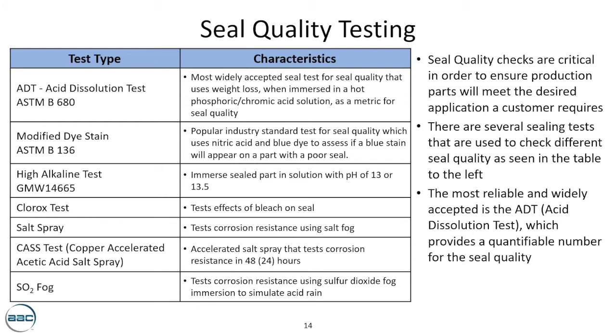The third one is the high alkaline resistance test. In this particular test, a part is immersed in a solution of a high pH, which ranges between 12.5 to 13.5, usually 13 or 13.5 pH. This test is used in the automotive and cookware industries, where these parts go through a lot of these rigorous solutions with high pH. The fourth one is the Clorox test, where we test the effect of bleach on the seal. Now, the next three are used to test the corrosion resistance.